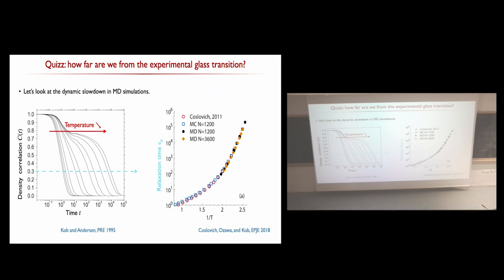So I think this is time for another quiz. In these simulations, we have this typical curve. We go to the point where we run out of steam. This corresponds to the last point that we can simulate, because then it takes too much time. And the question is, how far are we from the experimental glass transition? If you want, I can probably help a little bit. How many decades has the liquid slowed down here? 6. And in experiments, how many decades is it, from very fast liquids, 10 picoseconds, up to 100 seconds? 12. Okay, so how far?